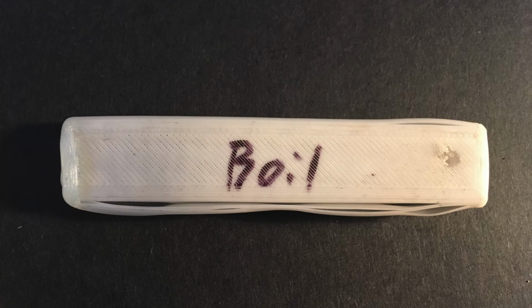Some of the alcohol treated samples, particularly the ones that sat overnight, delaminated easier than the other prints did. But some of the boiled samples delaminated as well if I cook them too hot, and you can see the extreme shrinkage here. So it's quite possible that some of these prints were just under-extruding a little bit, which is why I printed tons of them. So further work, further testing, whatever. It's quite obvious that this was just something that I had done for myself.